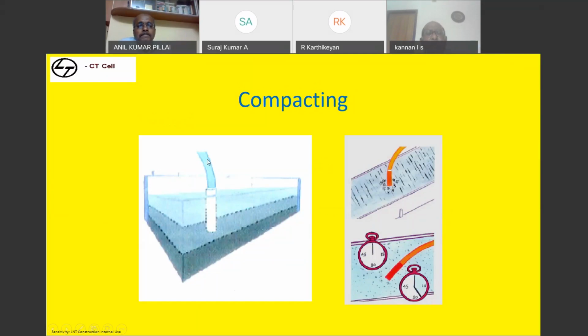So the vibrator needle has to percolate to the previously laid concrete, as I said, so that the stitching of this layer and this layer happens. That is the reason if stitching has happened, we will not be able to see the layer lines on the sides. However many layers you poured the concrete in, we are not able to see them because the stitching generally happens. So the vibrator needle has to percolate on its own weight without any pressure to the bottom of the layer, at least 250 mm, and the stitching should happen. So this is the process of compaction with the needle, and it has time limitations.